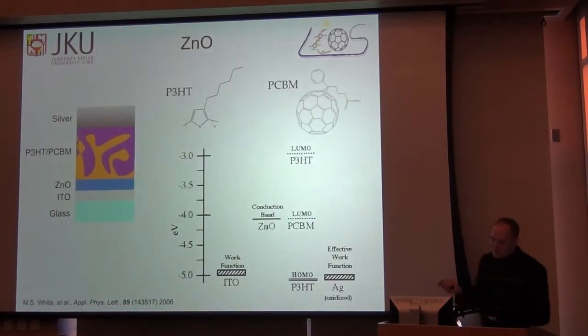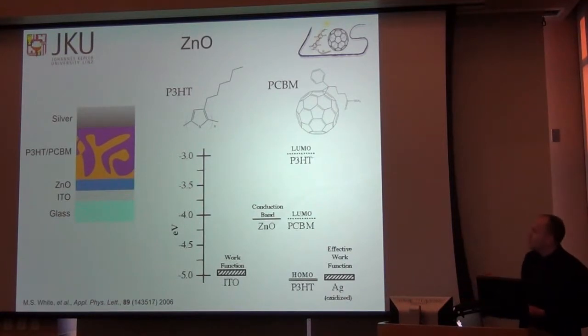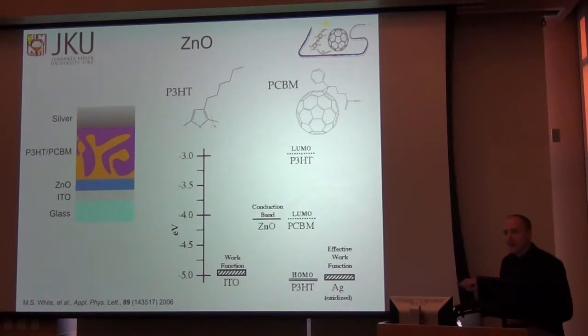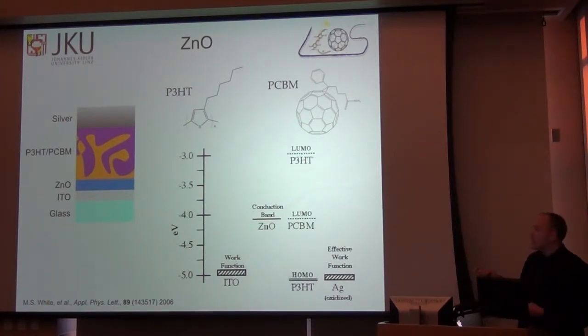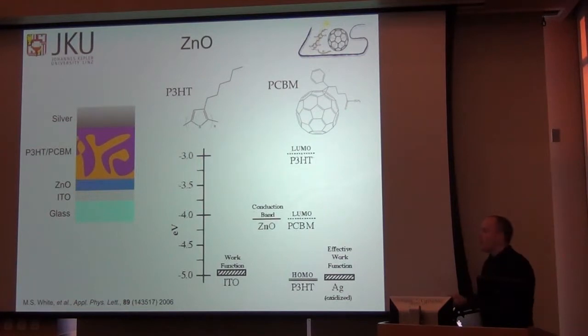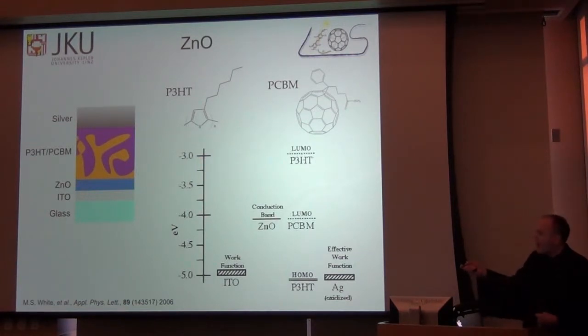So at first, we used zinc oxide, and we produced it from a solution of zinc acetate, which requires annealing at 300 degrees C to convert it to zinc oxide, which means that we can't put it on top of the polymer because the polymer would burn away. So we put the zinc oxide underneath, spin-coated the polymer fullerene blend, and capped it with a silver layer. And because now the electron transport layer is on the bottom, we call this an inverted device, a name which has stuck and become very popular.